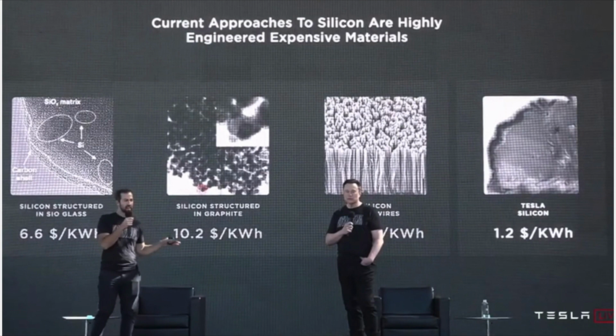But I guess this will be one of the bottlenecks for their volume production, because believe me, the work done at Stanford, Professor Yi Cui is one of the respected scientists, and he has been working on silicon for the last 15 years. But the biggest problem is, as you know, when you put lithium into silicon, it expands and it breaks, because it expands 4 times. But on the flip side, you get amazing capacity. It goes from 370 for graphite to more than 10 times that.